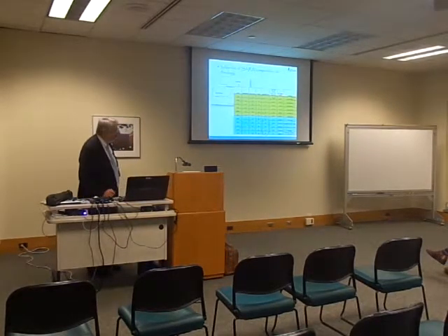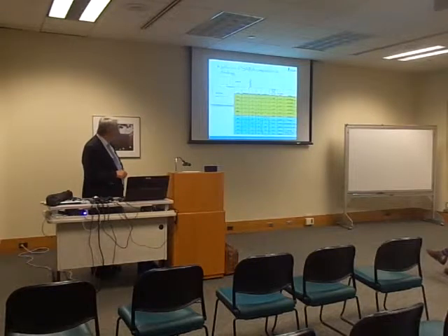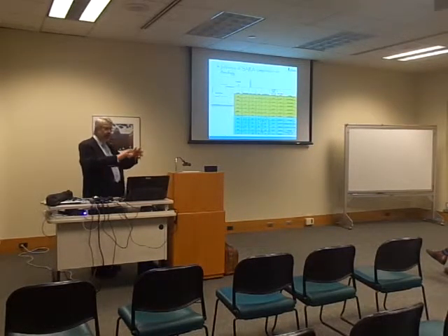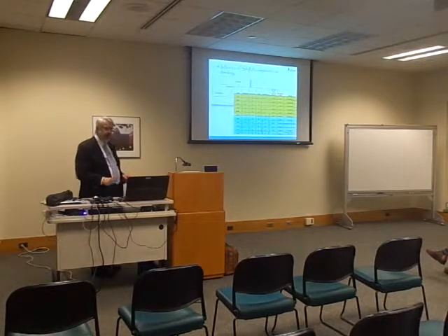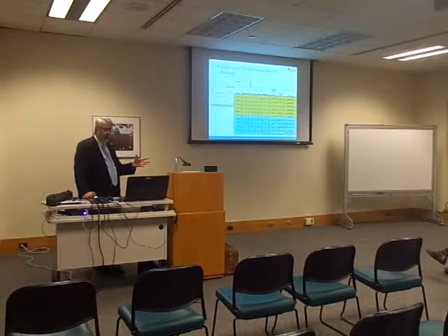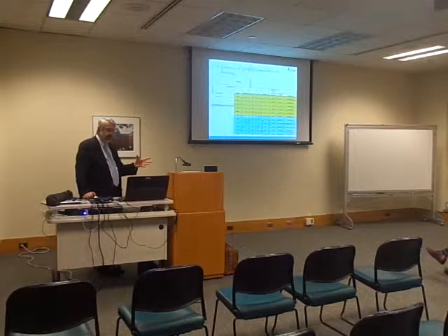This is a summary of the features of the rejuvenators in terms of this attempt to split them in groups, in particular chemical groups. The bottom here are the bitumens we use, the 8 bitumens, and you notice that they are rich in what is known as asphaltenes. Asphaltenes are a type of molecules in bitumen which happen to be stiff and large.